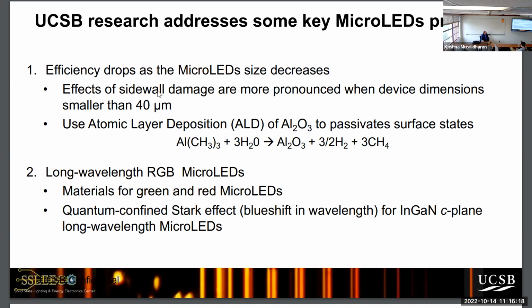And so what we did is we employed another technique in chemical vapor deposition. And this is called ALD, or atomic layer deposition. So as you refurb your clean room here, you should buy a couple ALD machines, because this is now control of the chemical vapor deposition process at the atomic level. And it's a modification of MOCVD where, instead of reacting ammonia with a metal organic, we react water. And so you react trimethyl aluminum with water. And in particular, you pulse these in separately. And what you get is a perfect aluminum oxide on the device.